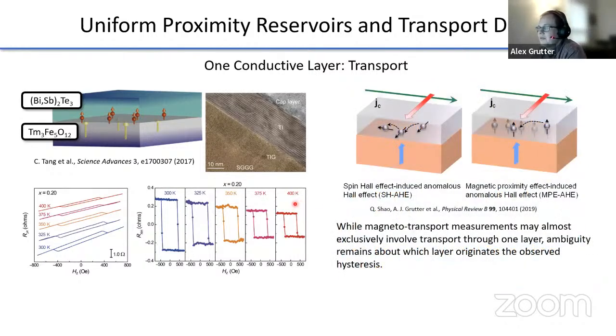So how do we understand this? Well, one of the things we need to try and get our heads around is figuring out, is there a real magnetization induced in the system at all? And here we have to point out that a lot of the measurements that people tend to do on these systems are transport measurements. The idea is that you take an insulating material and you flow current primarily through the topological surface states in your topological insulator. And if you see an anomalous Hall loop, the hope is that you're not really probing the insulating state, but just the surface state. And so if you see a Hall loop, then that implies a magnetic proximity effect.